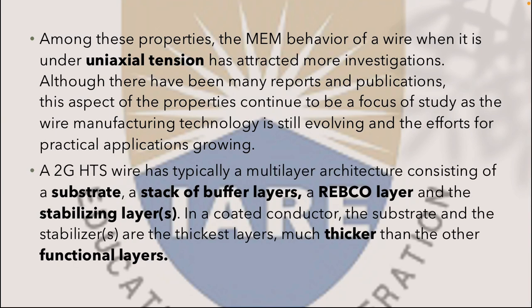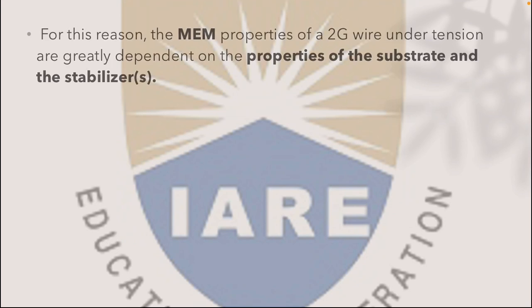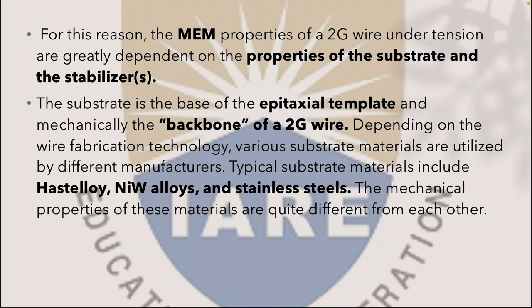A 2G HTS wire typically has a multi-layer architecture consisting of a substrate, a stack of buffer layers, a REBCO layer and a stabilizing layer. In coated conductors, the substrate and the stabilizer are the thickest layers, much thicker than the other functional layers. For this reason, the mechanical properties of 2G wire under tension are greatly dependent on the properties of the substrate and stabilizer. The substrate is the base of the epitaxial template and mechanically the backbone of a 2G wire.